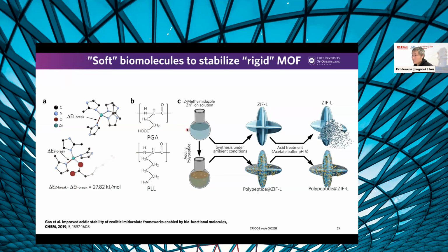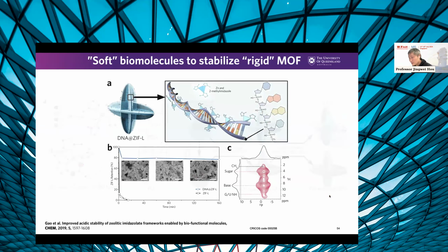How about in reality? We compare 2 types of MOF. One is just pure MOF, which after synthesis we put in a buffer of only pH 5. It almost starts decomposing immediately. But after we compose it with the polypeptide, it forms bonding with the MOF. As you can see, it's actually making the MOF much more robust. That provides additional chemical protection for the MOF. That's quite exciting. So the polypeptide works.